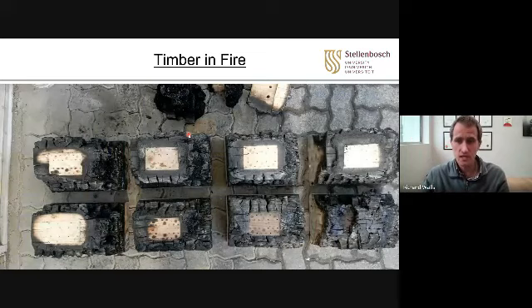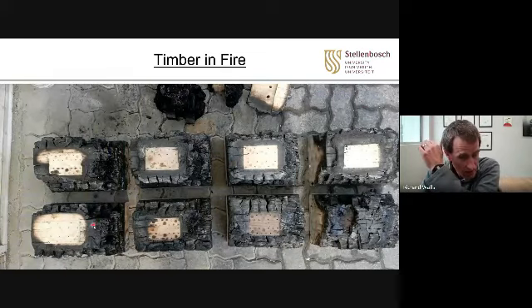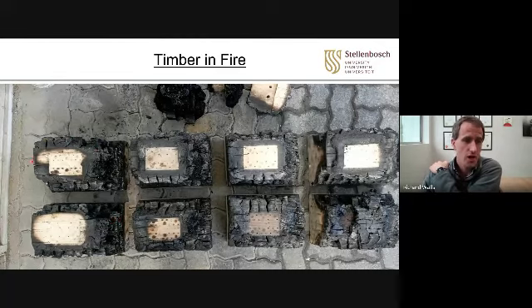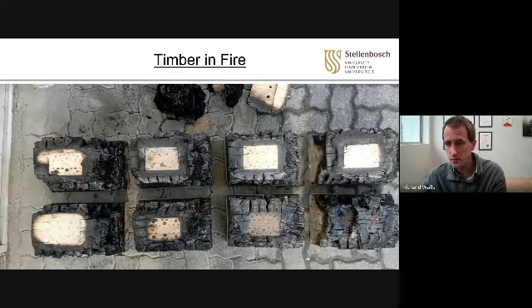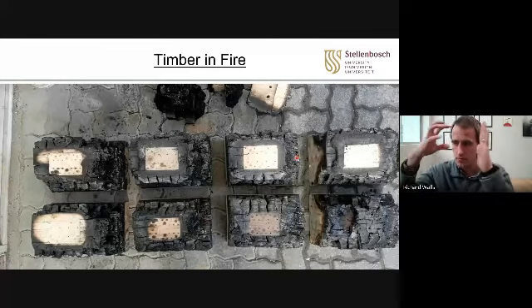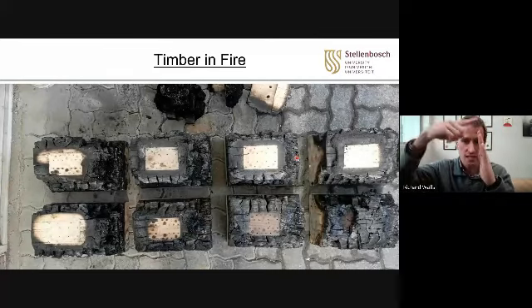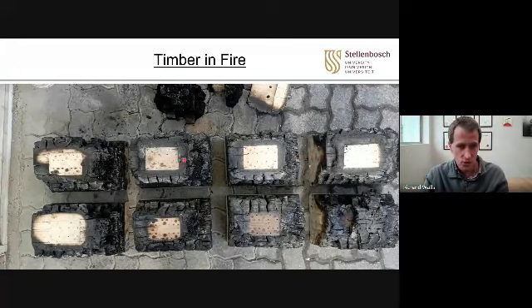So for instance, here are some connections that we tested in fire. And you can see there very clearly the char versus the non-char. Different connections are protected in different ways. These ones on the top had passive protection in the joint because there was a beam and a column, and where they tied together, we sealed the joint. So you can see where the joint was sealed, it performed well. These ones had no sealing, but that was a very tight joint, so the fire couldn't penetrate.